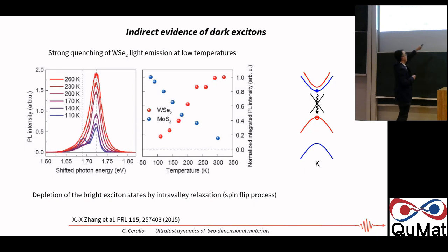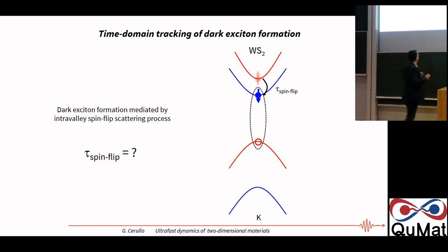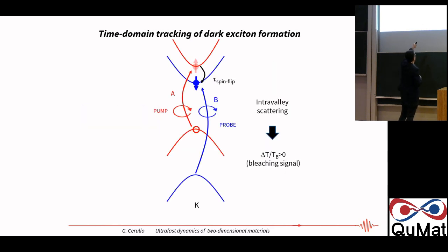So what we wanted to measure is how long it takes for the spin to flip. And how do we do it? We have to do a rather sophisticated experiment. So we have to pump with circularly polarized light and we access the A exciton. And then if we probe with the same circular polarization, but now looking at the B exciton, we will essentially only see a signal when there is this spin flip. So this signal will not be present at the beginning because we have not touched this transition. But as soon as there is this spin flip, we will see this bleaching signal rising.